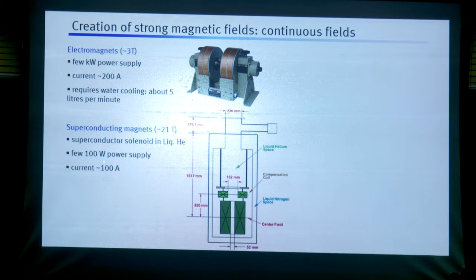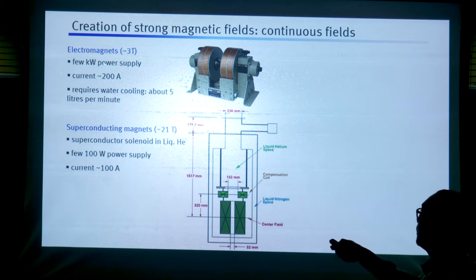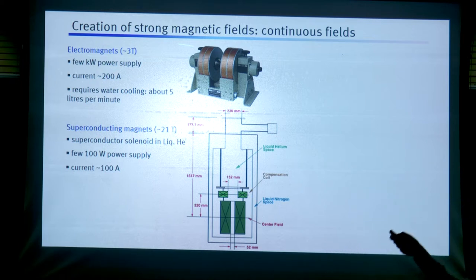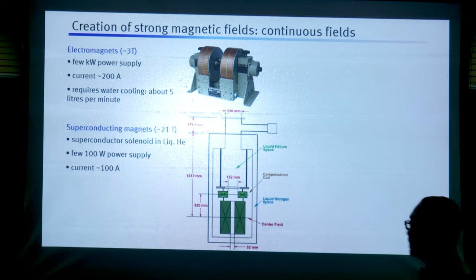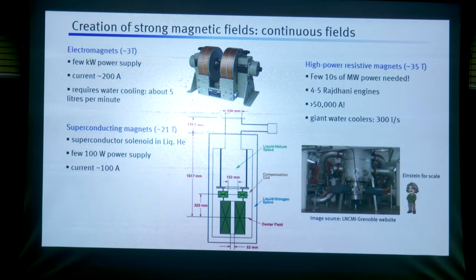So then you pass some 100 watts of power or something, compared to about 3 kilowatt or 10 kilowatt here in this. So this power consumption is much reduced, because now the material has become superconductor. So there is no power loss. And the current of about 100 amperes, you can go up to 21 Tesla these days. But what if you want even larger fields? Well, we want larger fields.